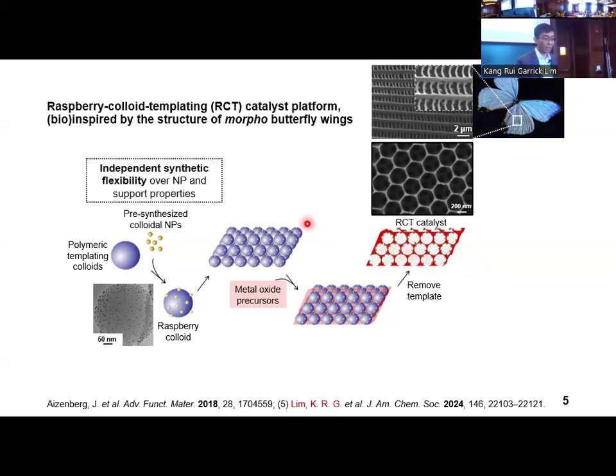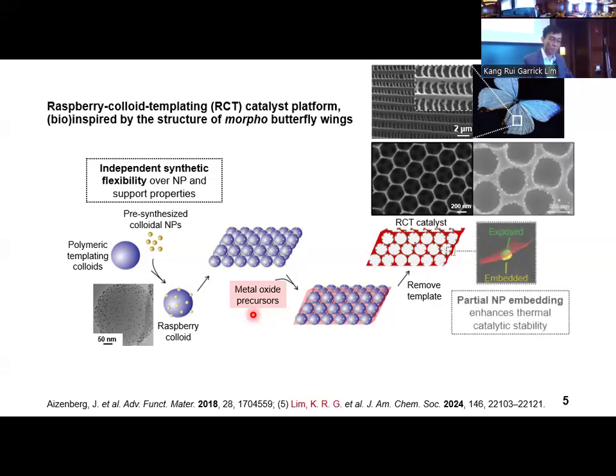One, the RCT method uses pre-synthesized colloidal nanoparticles, which decouples the nanoparticle and the support formation steps from each other for independent variation of either component. You will notice that I do not label the chemical identity of the nanoparticles, templating colloids, or support precursor to highlight and illustrate the chemical flexibility of this RCT platform.